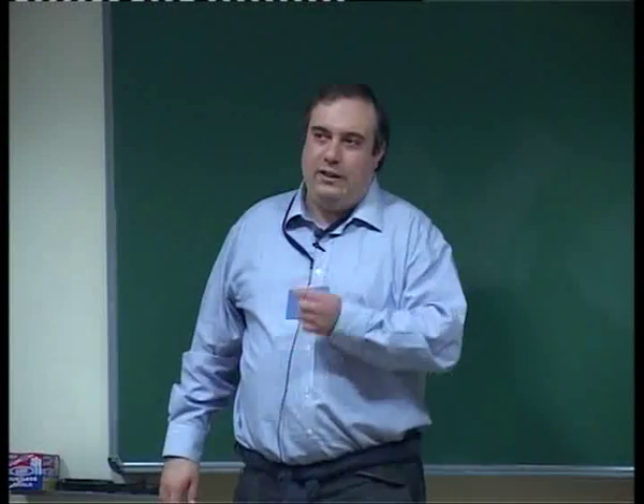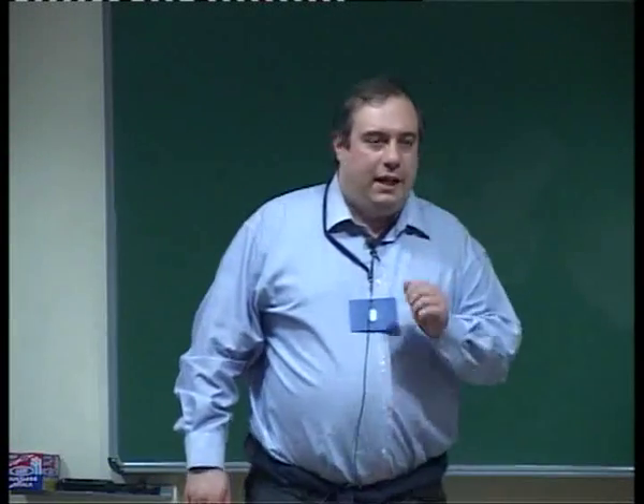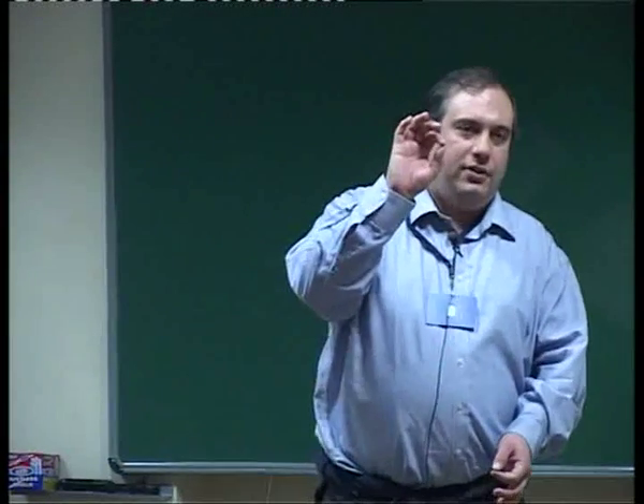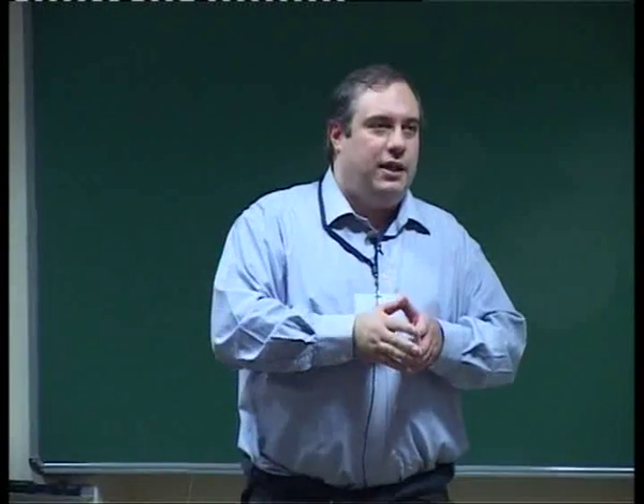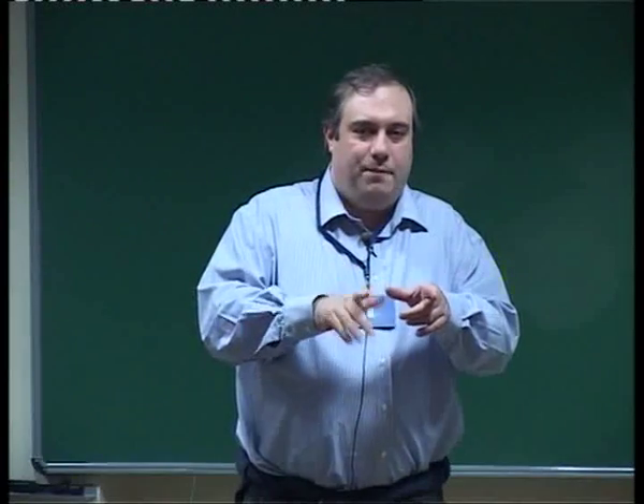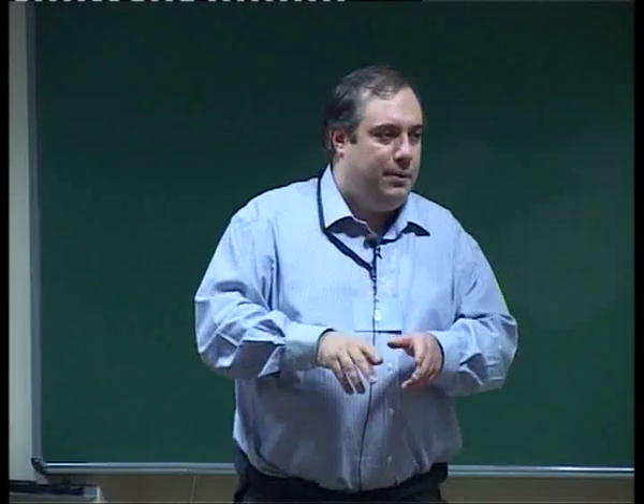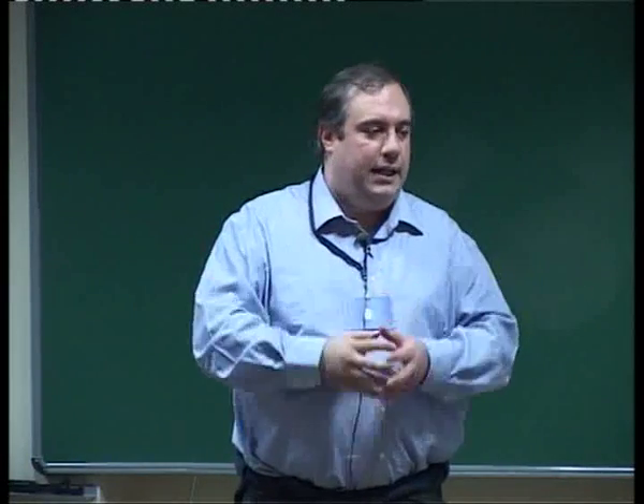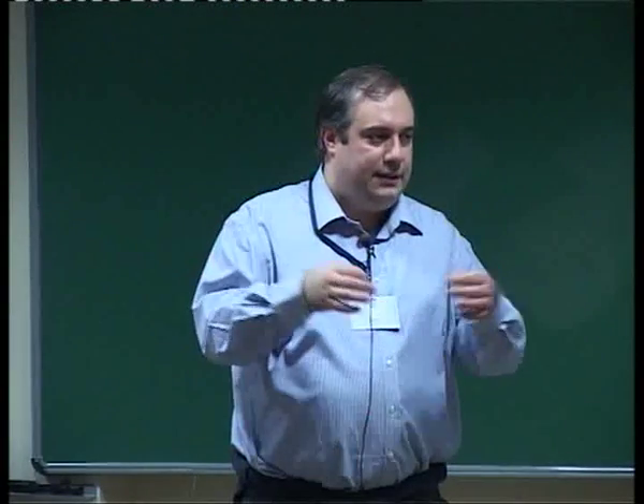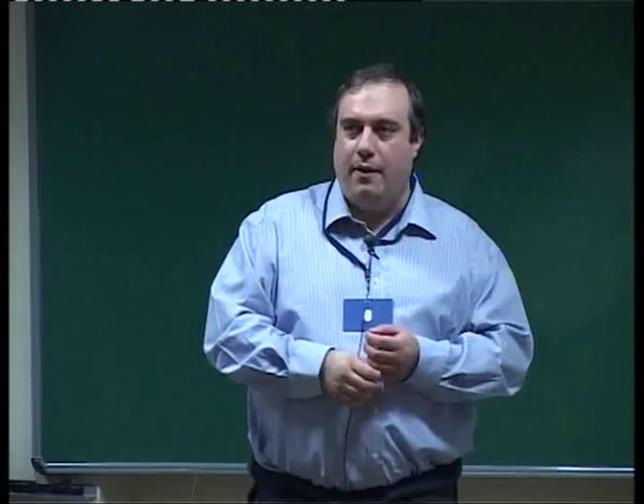The responsivity in graphene, of course, once you generate the electron-hole pair, those 2 guys, they want to recombine, they don't want to get out. So in order to get them out, you need a potential. So the easiest detector, you take a piece of metal with a graphene, there's a built-in potential, there's a different work function, and it creates a potential at the interface that separates the electron-hole pair, or that takes out the electrons and the holes from the other side.